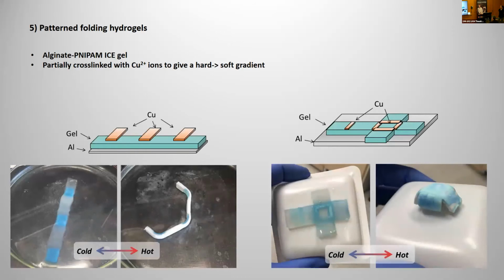So these schematics here sort of show where the copper electrodes are being placed on the gel. And if you tactically insert these regions of more hard material, when you go and actuate it, because there's poly-NiPAM in it, so when you put it into hot water, it will not just shrink in every direction, but it will fold in a complex pattern or shape. So again, not totally sure of the application of this, but it looks pretty cool, and I'm sure there will be some great people among us who can come up with a good application.